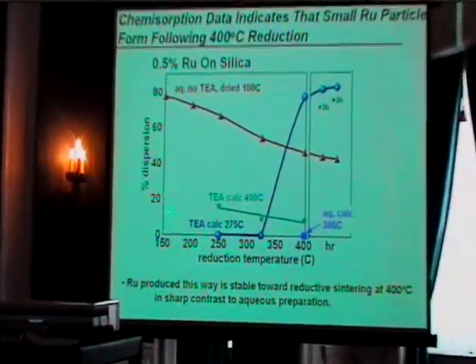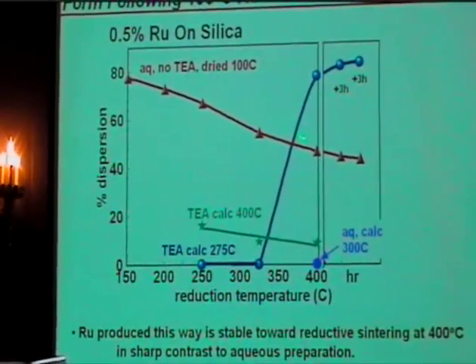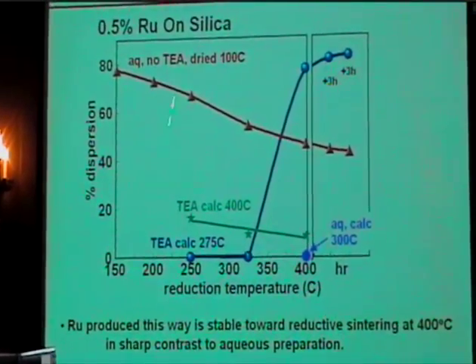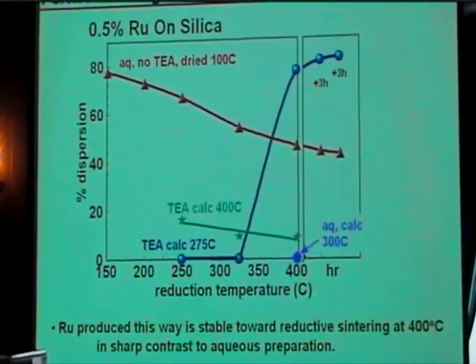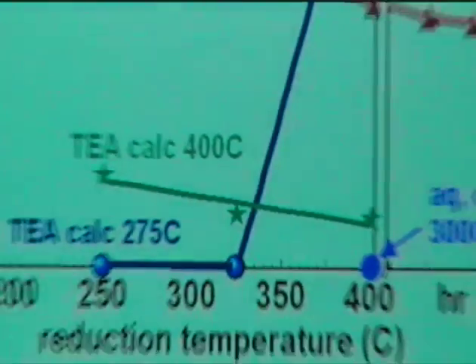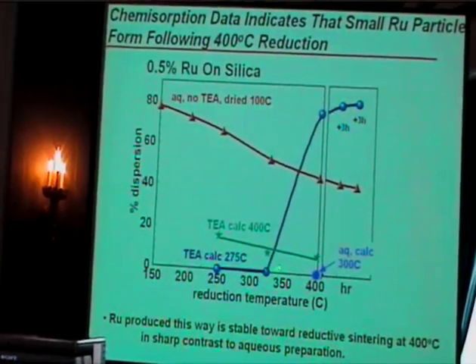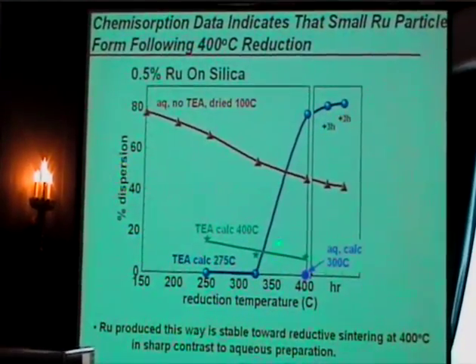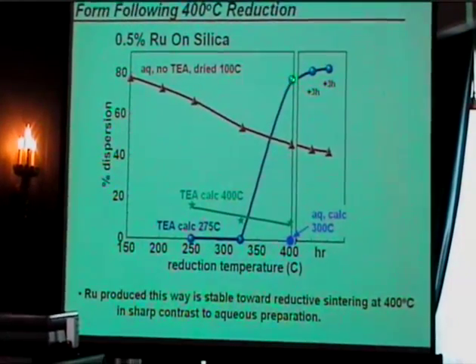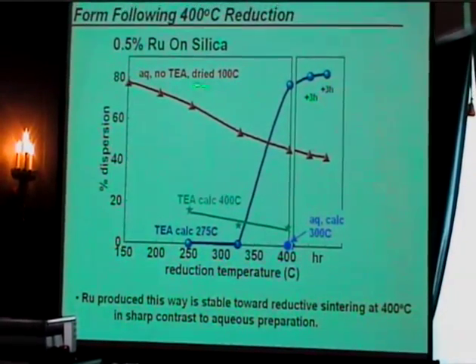But what happens now is you do these reductions at subsequently higher temperatures, the ruthenium dispersion goes down. Okay, something's happening, we're losing metal sites as we're going up in temperature. It's not stable. If we take that calcine complex, that's these blue circles here, remember I just showed you on the last slide, you have to go to high temperatures to reduce it. So at the low temperatures, nothing. Once you get above over here and you're up to 400 degrees C, you also get a very high dispersion.